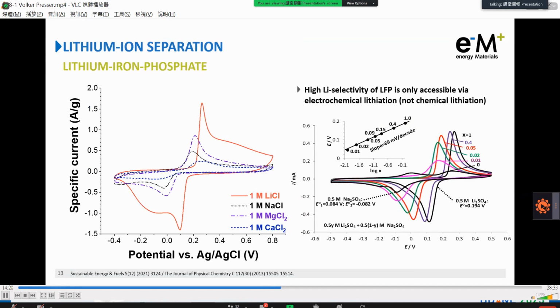Indeed, 10 years ago, in a collaboration with our friends in Israel, Doron Aurbach and Mikhail Levi, we had already explored the lithium selectivity of lithium iron phosphate with electrochemical quartz crystal microbalance experiments, where we had a solution of lithium and sodium sulfate, and we saw a perfect fit where the trace of the potential versus the concentration fitted an almost exclusive pattern of the concentration of lithium. Only when starved for lithium was sodium also uptaken. It is thereby a very selective material indeed.